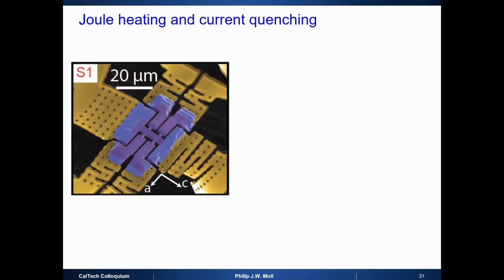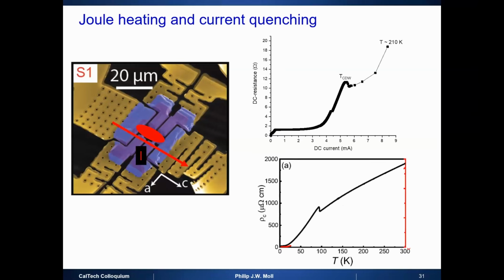And this is what we can get to quite naturally from these structures, because we can just blast it with current. We blast huge DC currents to that thing, joule heat it, while the system stays at base temperature, or that the chip stays at base temperature. Of course, you want a short current pulse, right? You don't want to heat up the entire cryostat with this. And then this is what you see. So here, this is the DC resistance of the device as a function of current bias. The cross section is in square microns, so we're talking about tens of thousands to hundreds of thousands of amps per square centimeter. This is a lot of current, okay?